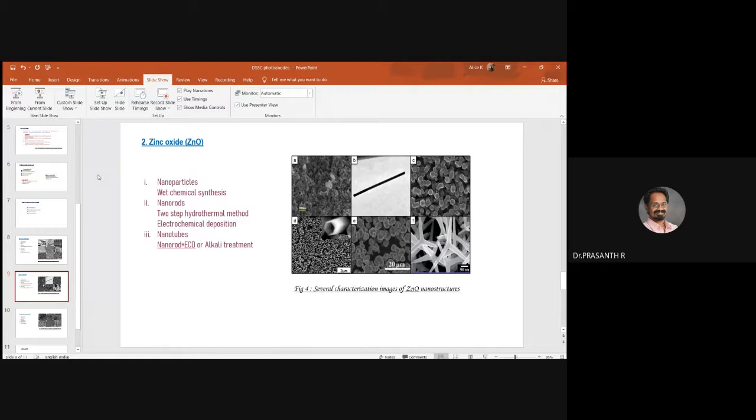It is the most simple and cost-effective method for the fabrication of zinc oxide nanorod arrays. In this method, zinc oxide nanorods are deposited on a conducting substrate like FTO coated glass using a 3 electrode electrochemical setup. The electrolyte consists of a zinc precursor solution with potassium chloride saturated with molecular oxygen.